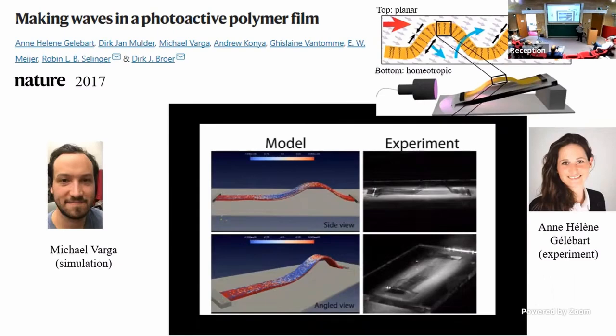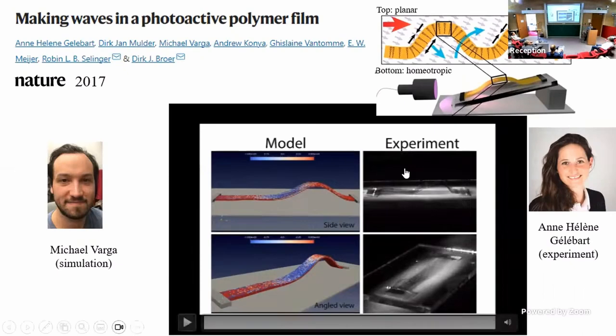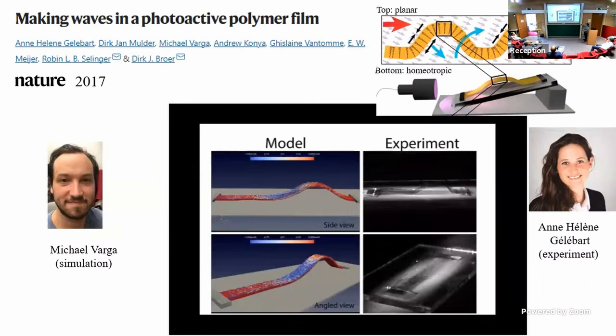And then when they shine UV light from the left side, they saw this continuous oscillation process with waves moving away from the light. But if they mounted the same sample upside down, so the homeotropic one is on top, the waves move toward the light and much more slowly. And Dirk wanted to know, what could possibly be causing this? So this picture at the top shows planar on the top, homeotropic on the bottom, shine UV light from the left side, and you get these dancing waves.